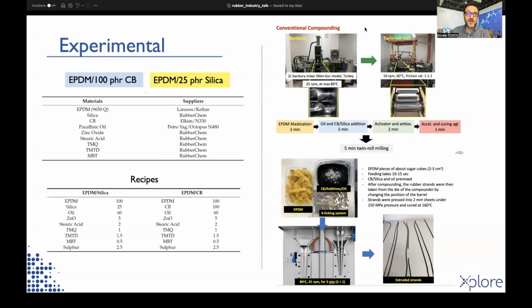The total mixing time, including the twin roll milling, was 15 minutes. On the other hand, we prepared the same compounds using a microcompounder which was operated at 25 or 100 RPM at 80 degrees Celsius and for only 3 minutes total mixing time. It's important to note that both processing methods were not optimized for the compounding of EPDM using silica or carbon black.